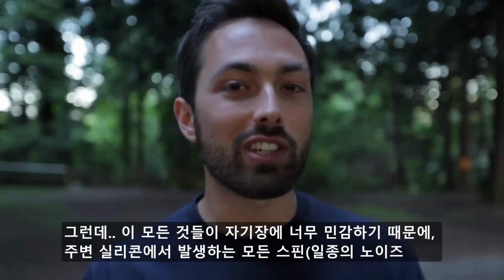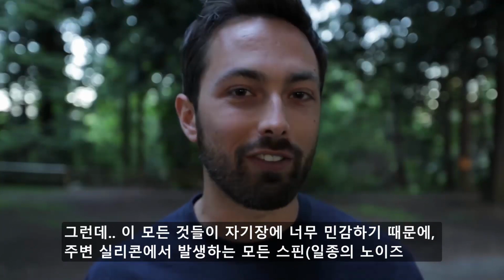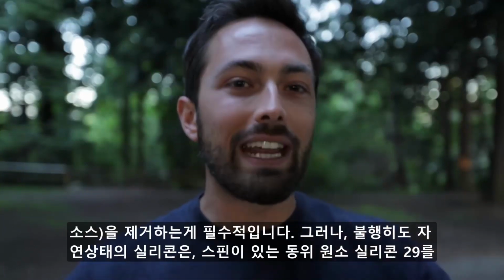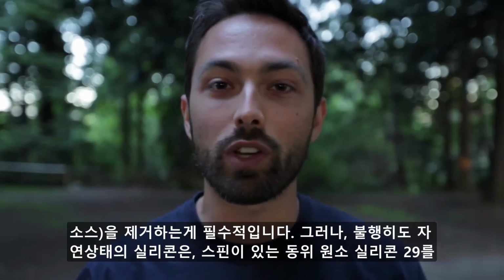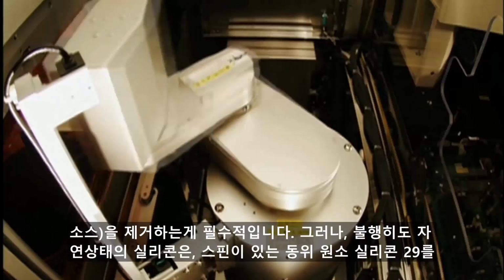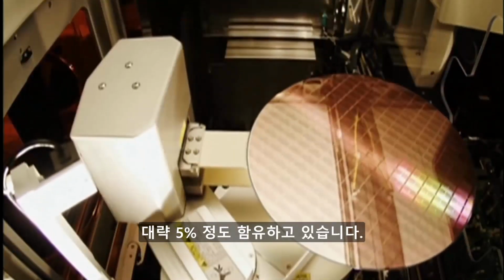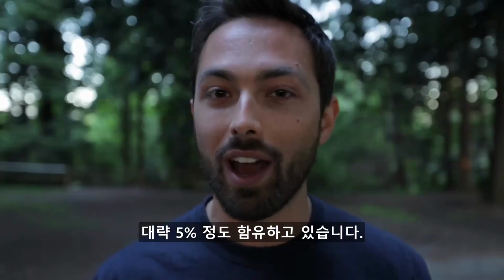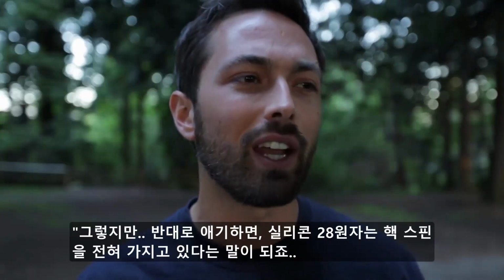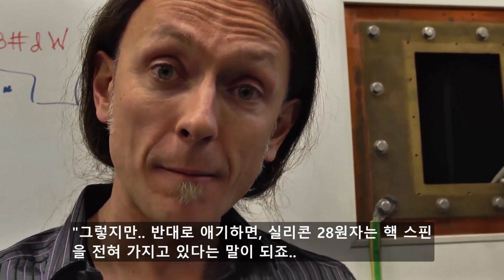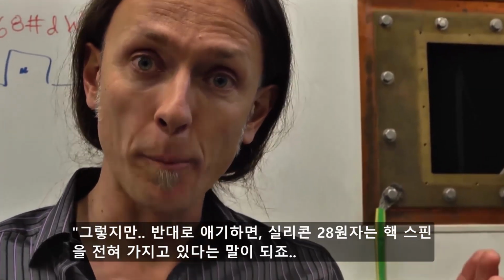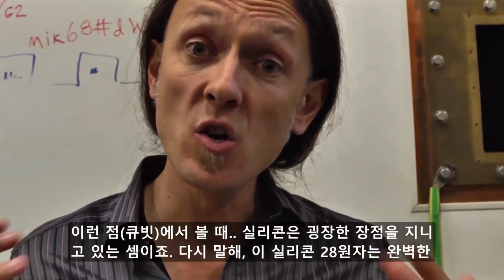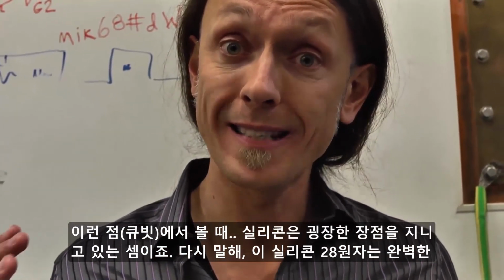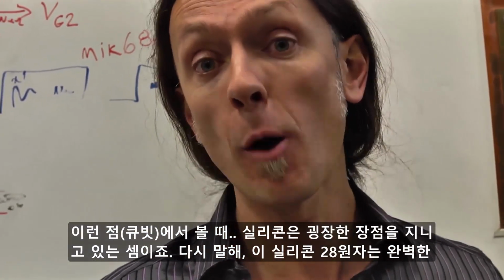Now, because all of this depends so sensitively on magnetic fields, you need to make sure to eliminate all spin from the silicon crystal. But unfortunately, natural silicon contains about 5% the isotope silicon-29, and that does have a spin. But in fact, the beauty of silicon is that it has this isotope called silicon-28 that has no nuclear spin. The nuclear spin is 0. So it's a completely non-magnetic atom.